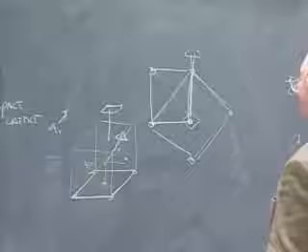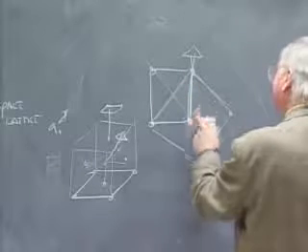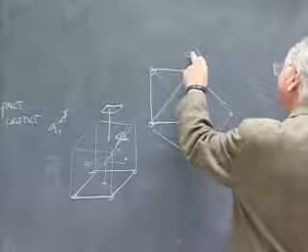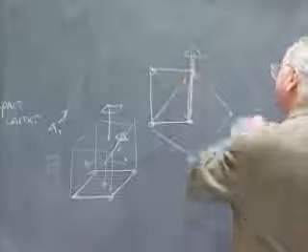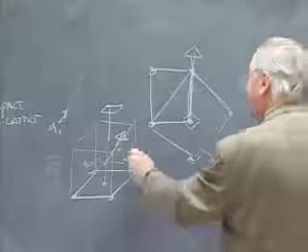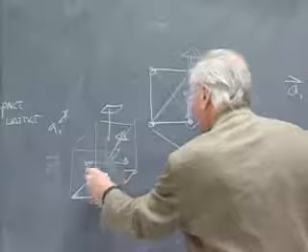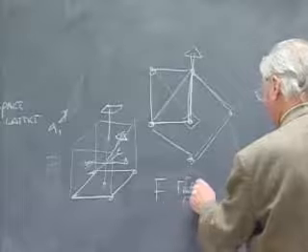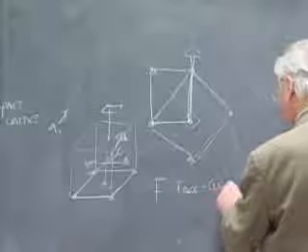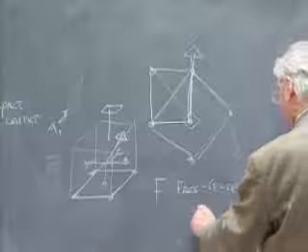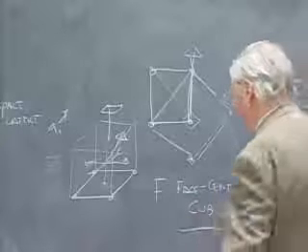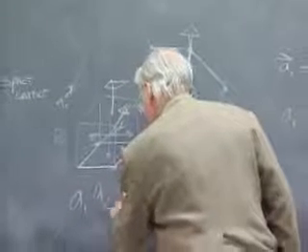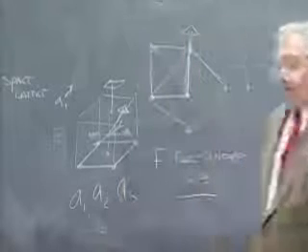faces of the cube. So it's only if I notice I can make a double square base to the cell. Again, put the threefold axis of a cubic symmetry along the direction of the body diagonal. I generate lattice points in the middle of the other faces as well, and this gives me the lattice known as F, the face-centered cubic lattice. And the edges of the cell here are all identical, equivalent by symmetry, so they're labeled A1, A2, A3.